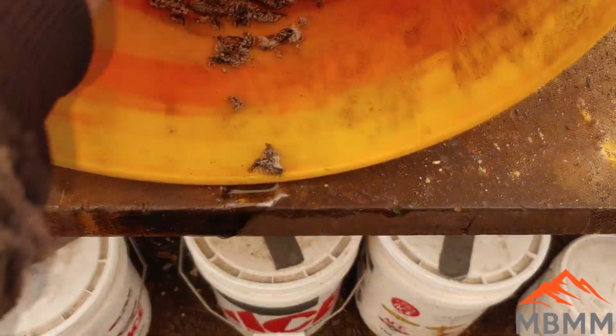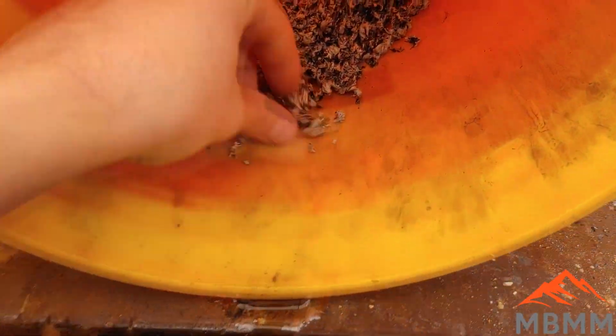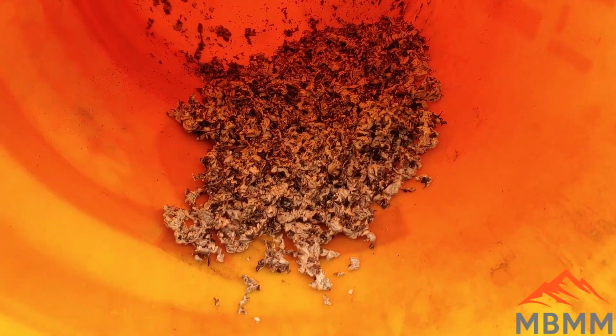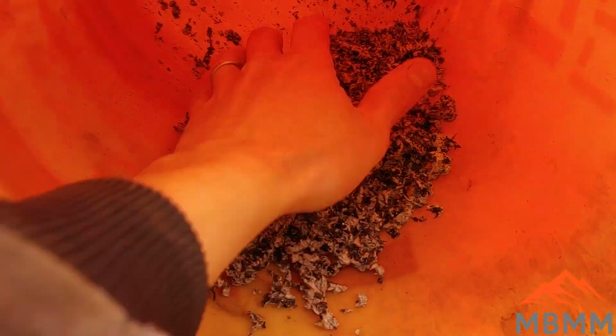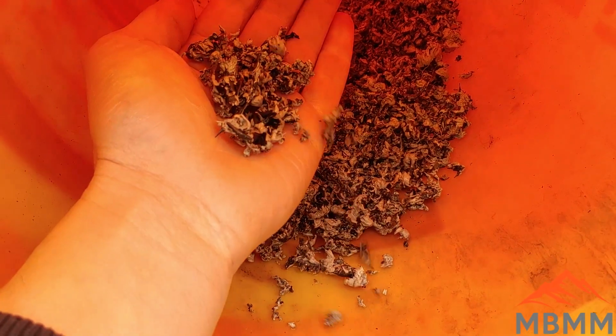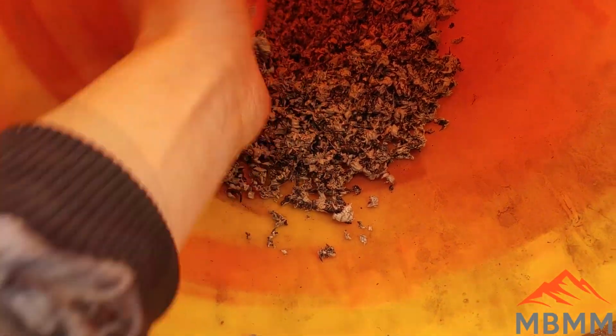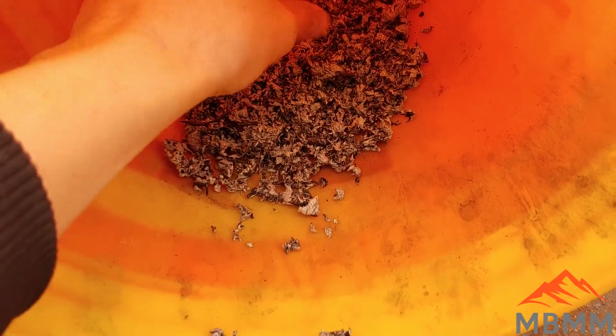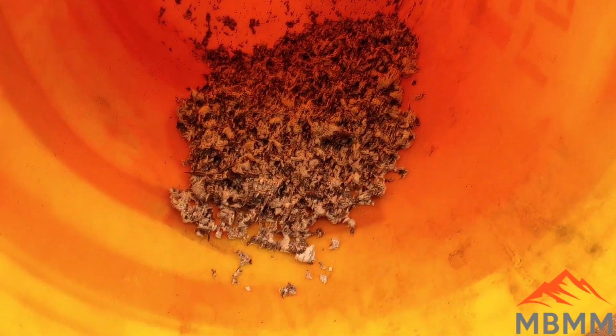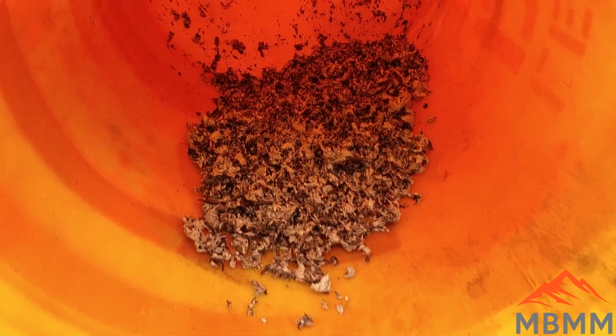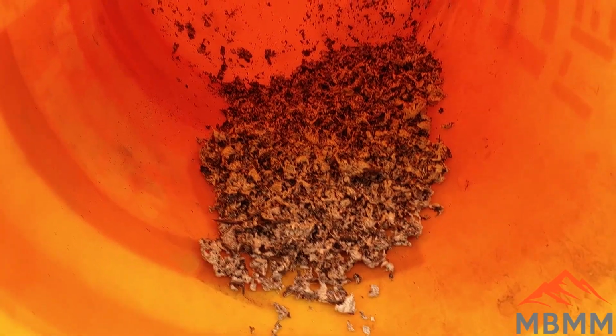And the whole reason we're doing this is because iron is pretty hard to cupel out. It takes a lot of lead or bismuth to oxidize the iron and get it out of there into the cupel. And so I'm trying to get rid of as much iron as I can before I go to cupel.